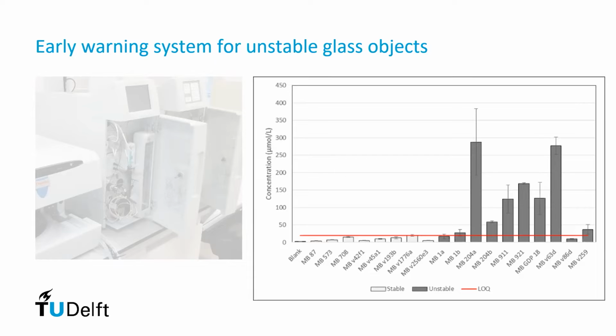And we were able to identify that for the unstable group, so the darker gray bars, we do see elevated concentration of these ions on the surface, even though you don't see any very clear moisture accumulation on the surface. So that was an interesting outcome, and that sort of gives confidence that we could identify these unstable glasses in an early stage. Next slide, please.